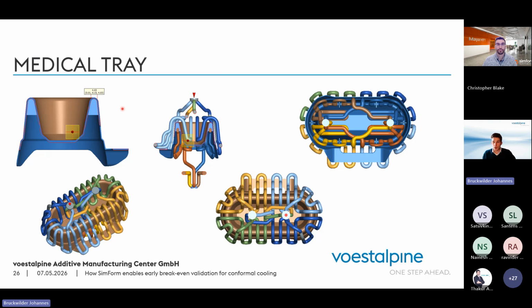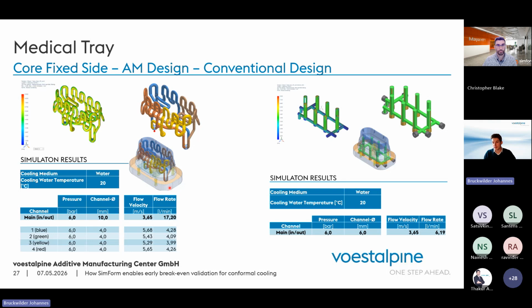You see it here. What we are doing is we have a look at the plastic part. For example, here is the constraint of 4 millimeter from here to here. But 4 millimeter, as you see it here, we can enter into that area. That's not a problem. And that's important, how you apply those channels. You see also that there is a parallel connection, and really, really important is that these channels are balanced. Here you see 4 channels, and you see each flow rate of those channels, roughly 4 liters per minute. So they are equally balanced, and you have a good flow rate with it.